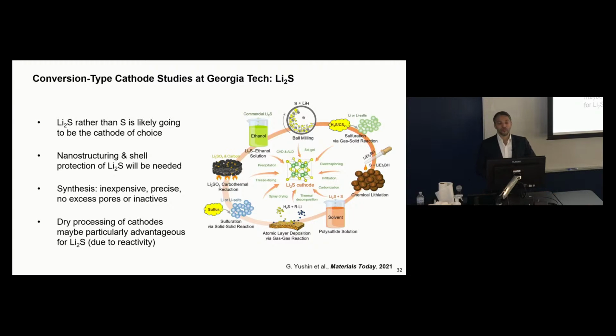In addition, I think all these materials would have to be nanostructured, similar to the way that silicon is nanostructured. They have to be protected from side reactions using shells. And the synthesis, again, has to be inexpensive, has to be very precise, and there should be no excessive pores of inactive materials in these composite particles. And now there is significant research, Tesla announced it, right, on dry processing of electrodes. And I would say lithium sulfide would be particularly advantageous to use with dry processing because it's more reactive. It's sensitive to moisture. So if you have dry processing, it's probably going to be advantageous even more for this particular technology.